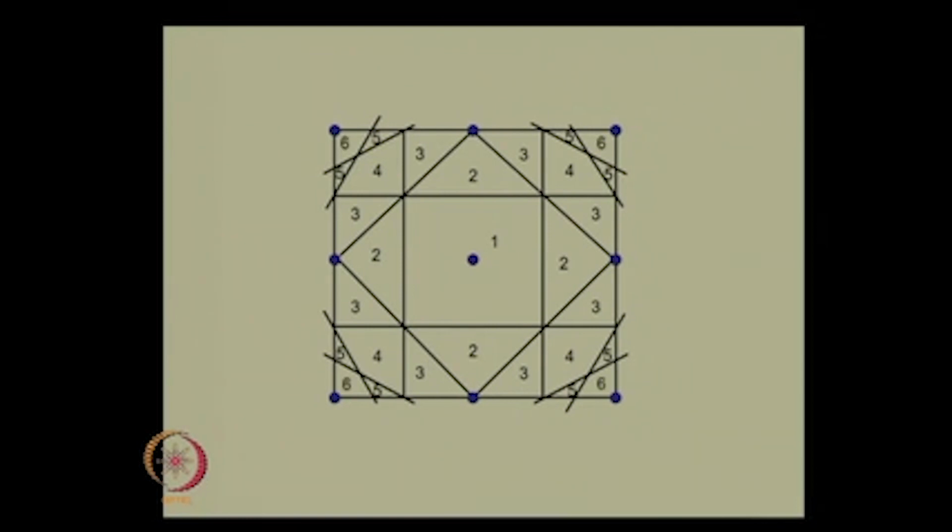So, for a simple 2-dimensional square array of points where we have only taken just 3 points on our screen, a 3 by 3 matrix of points, so we only have 9 points on screen, we have been able to identify for this lattice all the Bragg planes and therefore all the Brillouin zones. Okay. And please keep in mind always the Brillouin zones are defined with respect to the reciprocal lattice. So, originally we would have some material that would have a lattice in real space. Using the standard conventions for how you would get the corresponding reciprocal lattice, we would generate the corresponding reciprocal lattice.